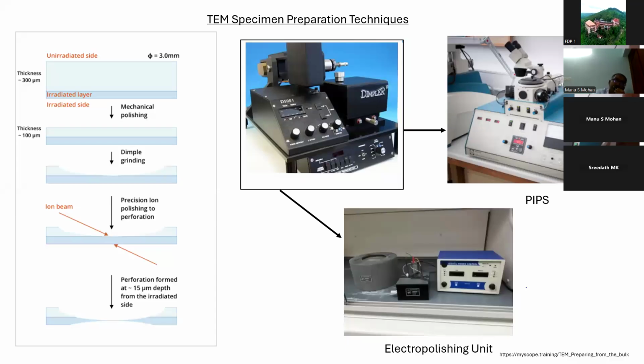In such cases, if you take the TEM, lots of artifacts will be seen, appearing as bent contours. When you try to publish in good journals, they may ask questions you have to justify. So here the specimen is polished from 300 microns down to almost 100 microns. Then that specimen is taken to a dimpler.